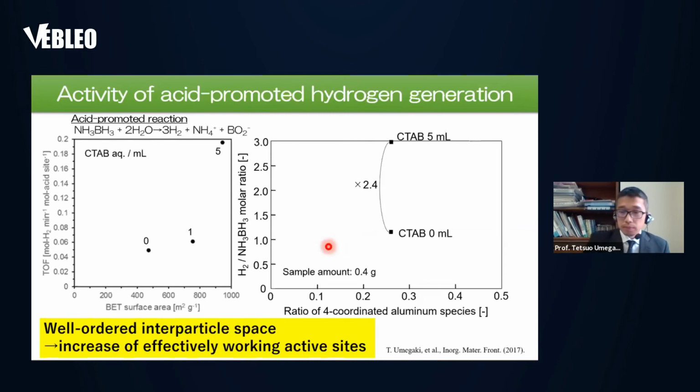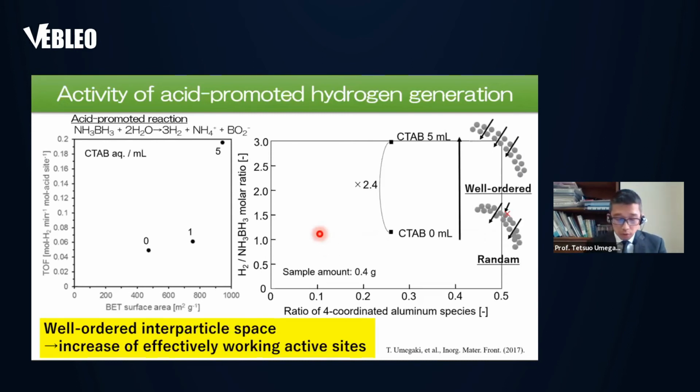As shown in these illustrations, the results suggested that the reactants easily diffused through the well-ordered shells' interparticle spaces, and as a result, the number of effectively working active sites in the well-ordered shells was much higher than that in the randomly integrated shells of the hollow spheres prepared without CTAB solution.